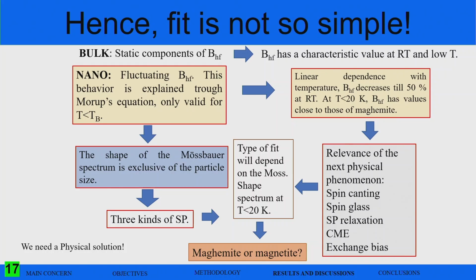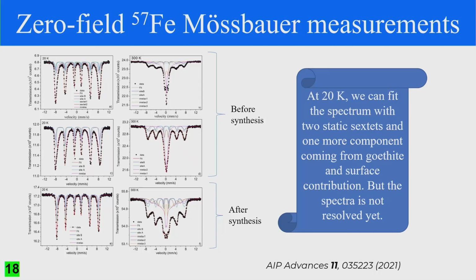More importantly, there are relevant physical phenomena that can also be studied using Mossbauer spectroscopy, of course combined with many techniques, like spin canting, spin glass, superparamagnetic relaxation, collective magnetic excitation, which was studied by our colleague yesterday, and exchange bias phenomena. Here are some zero-field 57Fe Mossbauer measurements. We analyzed that the sample before synthesis has intermediate relaxation at the center, marking a particle size distribution at 300 Kelvin. And after synthesis it produces highly distributed particles, but bigger than 10 nanometers. At low temperature, we can see two sextets can be used to fit the spectrum. It's a bulk sample, almost bulk. And we have here particles that have the Brownian contributions. Where this contribution comes from is not easy to say, and we are at 20 Kelvin.